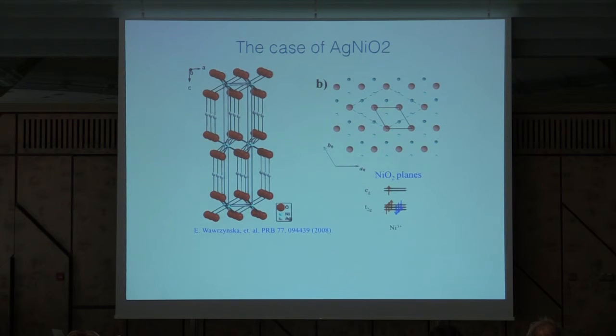So this is the guy. We became interested in this material a couple of years ago because, first of all, it has a triangular lattice. This is silver nickel O2. The crystal structure is delafossite. So you have these layers here. The nickel is in an octahedral environment. And when you see it from above, these are the nickel ions. They form a triangular lattice.